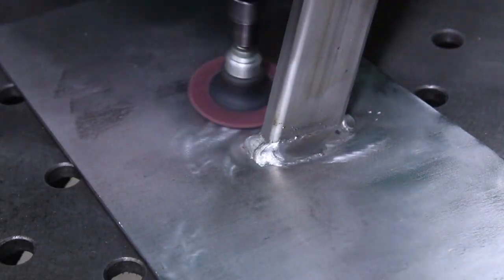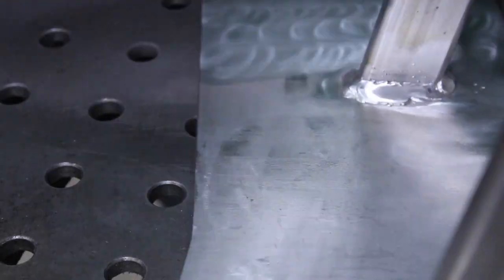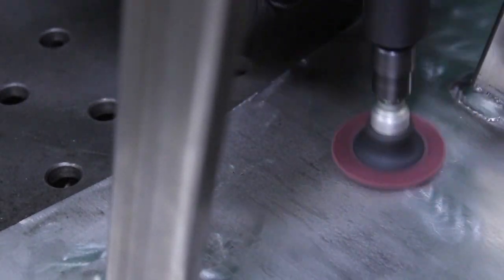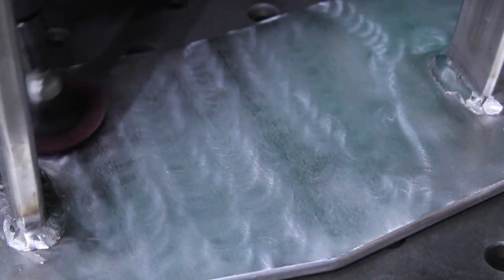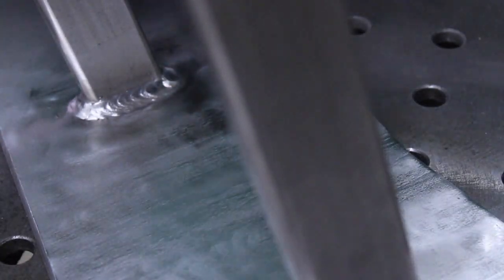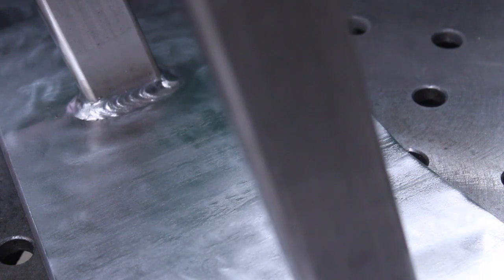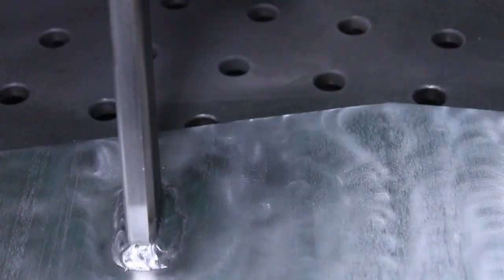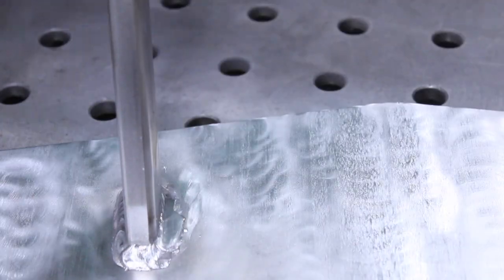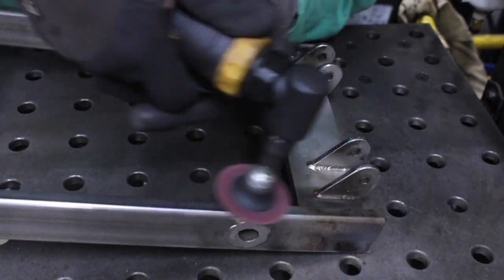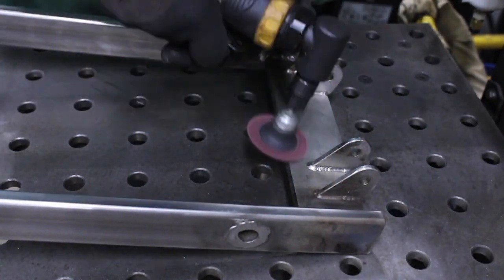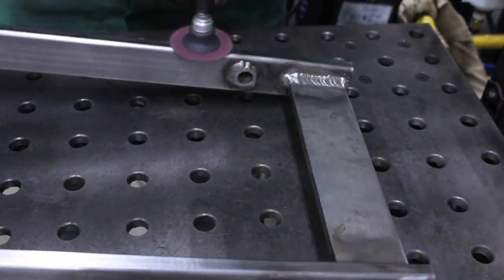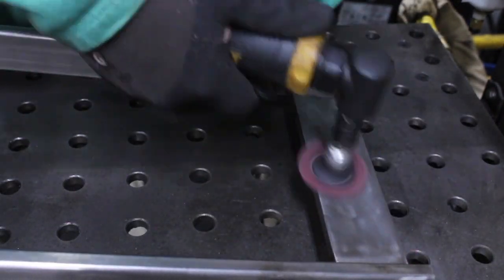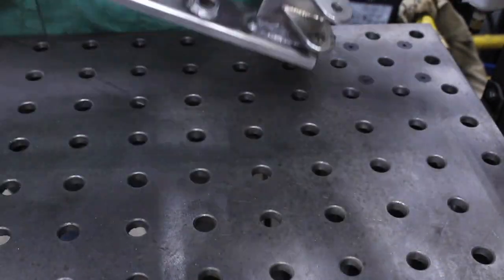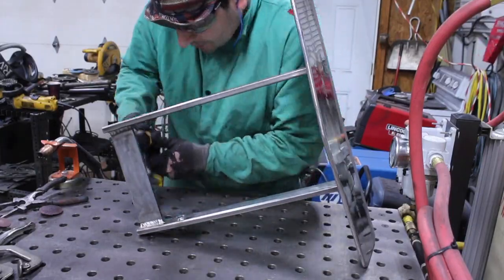Another reason is that it is more environmentally friendly, as it does not emit nitrogen oxide vapors that contribute to smog and acid rain and affect the ozone layer of the atmosphere. As per ASTM A967, we prepare a 5% by-weight solution of citric acid in water and a soluble gel agent so that it is able to cling to vertical surfaces, and we let that solution dwell upon the surface for 30 minutes at minimum at a surface temp of around 75 to 80 degrees Fahrenheit, or roughly room temperature. We then rinse and clean off the passivation solution and allow the piece to sit for about 24 hours so that the chromium oxide layer can develop and we can fully utilize those properties.